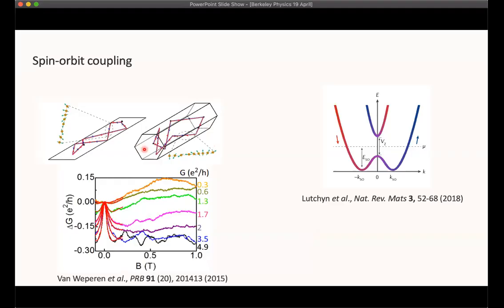In diffusive materials, as electrons bounce off of defects, sometimes they can take paths that enclose loops and return to a point along the wire here. And those multiple paths can interfere constructively and so localize the electrons. Localized electrons will contribute to an increase in resistance along the wire. However, in the presence of spin orbit coupling, there is a path-dependent rotation of the spin, and that ends up resulting in destructive interference, and so reducing the localization and reducing the resistance. At its heart, what we're measuring is just the resistance along the wire, but in doing so, we're able to back out the strength of the spin orbit effect. And so this is a method that we use to check that, in fact, we have the correct spin orbit energy to achieve the topological condition.